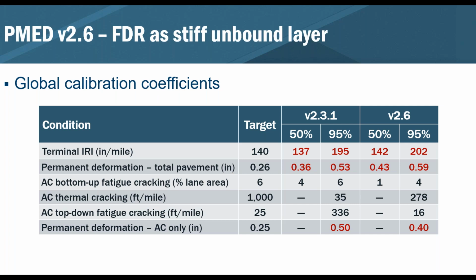I should have mentioned that with version 2.2 from Hari, from version 2.3, all the runs that we did, we actually used the Virginia DOT calibration coefficients. Now when you go into version 2.6, those calibration coefficients no longer are the same. So I abandoned all the calibration coefficients that we received from Hari and just went with the global calibration coefficients for version 2.6. So is it a direct comparison? No, because it's not calibrated to Virginia conditions. But I think it gives us a sense of how the new version would look in this analysis.